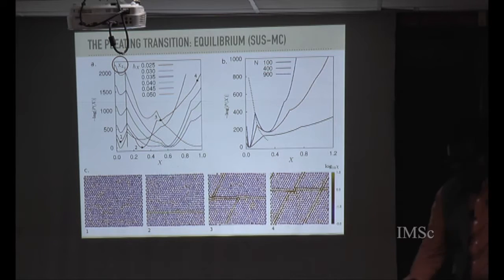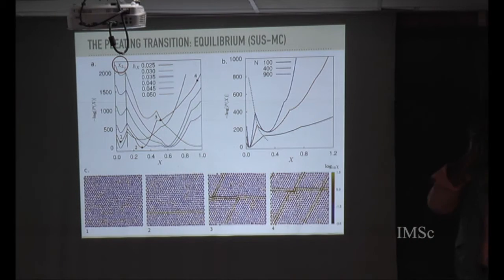This is what happens for small values of the field. When the field is increased, this is the first interesting result. If you started with a bonded network where dislocations can't really form, what the network does is that it pleats. It forms these pleats. And if you look at the free energy, we do some fancy Monte Carlo techniques, this sequential umbrella sampling, and you can actually calculate the probability distribution of this non-affine parameter, and you can plot them, and the inverse log of that looks like a free energy.